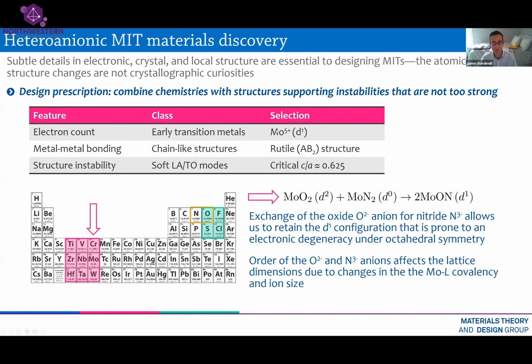And the idea is very simple. This table is now written sort of mathematically in a chemical formula where what we're going to do is take an oxide, molybdenum dioxide, combine it with molybdenum nitride, and what we get in the end is molybdenum oxynitride. And this will give me the electron count that's required to drive the metal-insulator transition. And it should be compatible with this rutile structure. That's the hypothesis. And so to determine whether that's true and we can drive an electronic transition from a metal to an insulator requires some experiment.